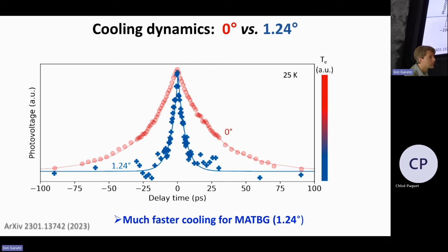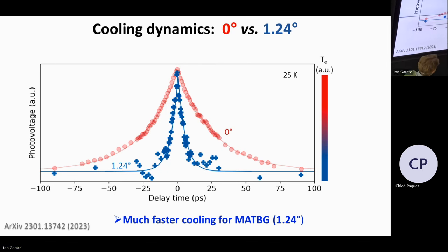Sometimes in cooling, I think you showed some examples a little bit later, the process is not purely diffusive or it's not just a time scale. But I suppose here it's just errors, right? The blue curve seems to have an oscillation on the left and not on the right. Yeah, that's a good observation. I'm not sure if it's real or not. Probably not because of the symmetry, right? Because there's really no difference between one of the pulses coming first. So the fact that we don't see it on the right probably tells us that what's happening there is indeed a smaller signal that makes it more difficult to fit nicely these cooling times.